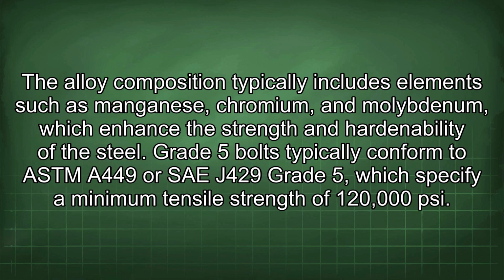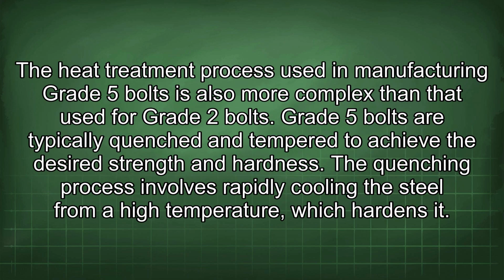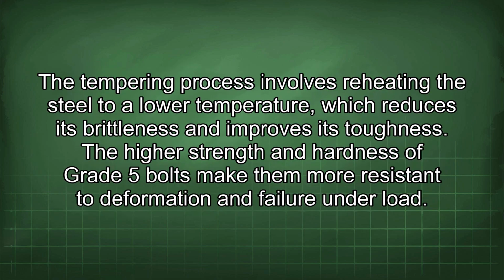of 120,000 psi. The heat treatment process used in manufacturing grade 5 bolts is also more complex than that used for grade 2 bolts. Grade 5 bolts are typically quenched and tempered to achieve the desired strength and hardness. The quenching process involves rapidly cooling the steel from a high temperature, which hardens it. The tempering process involves reheating the steel to a lower temperature, which reduces its brittleness and improves its toughness.